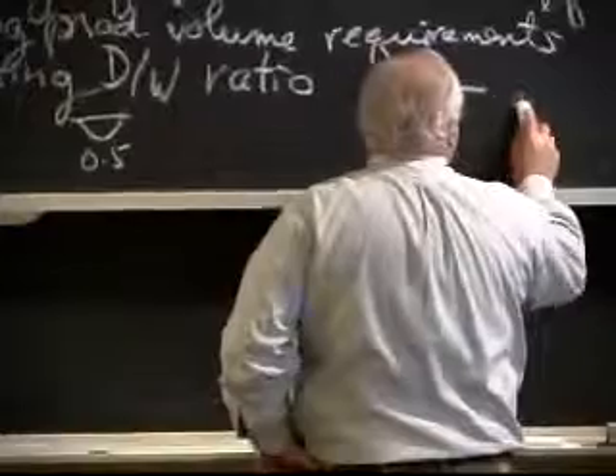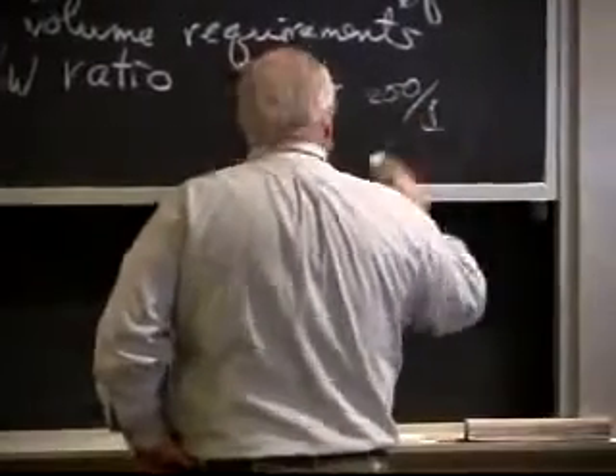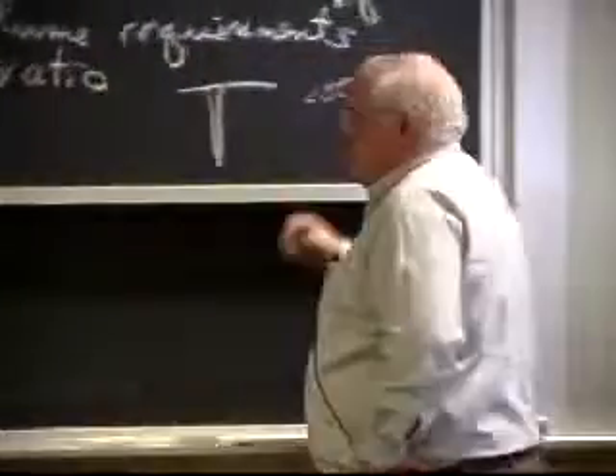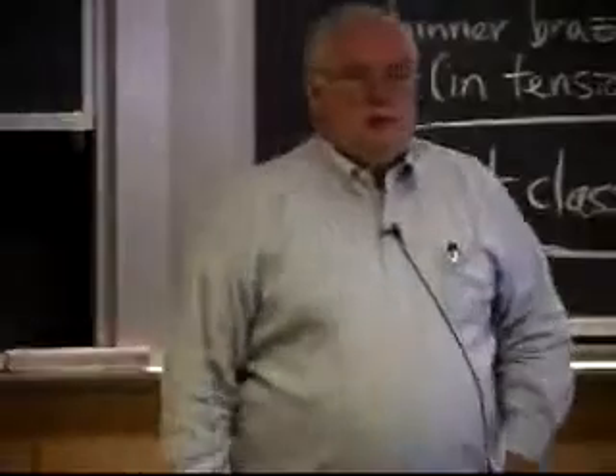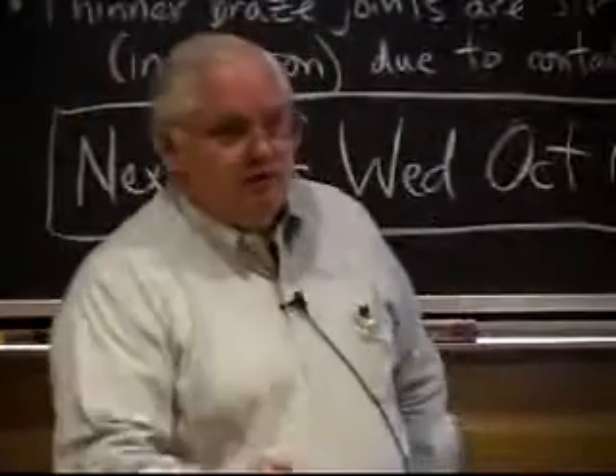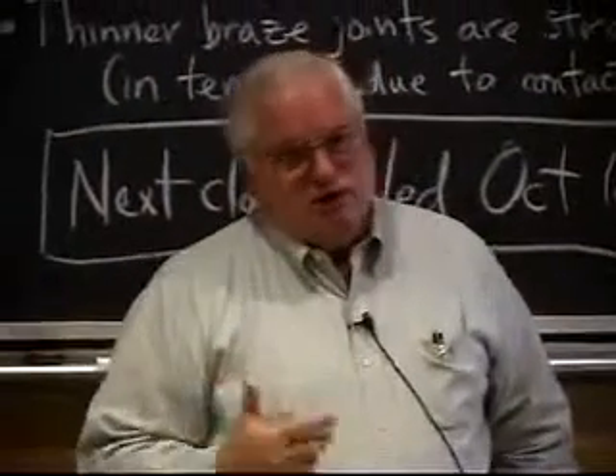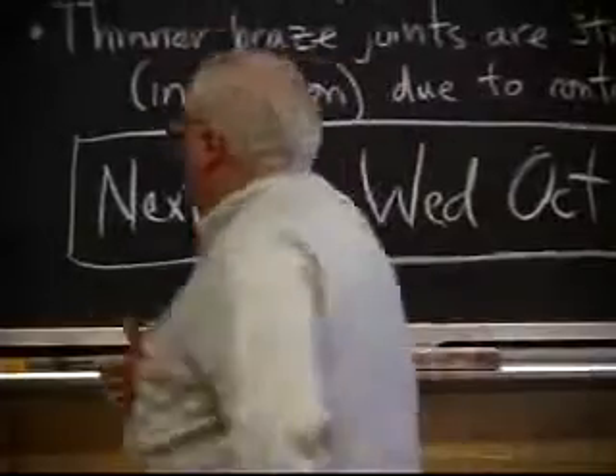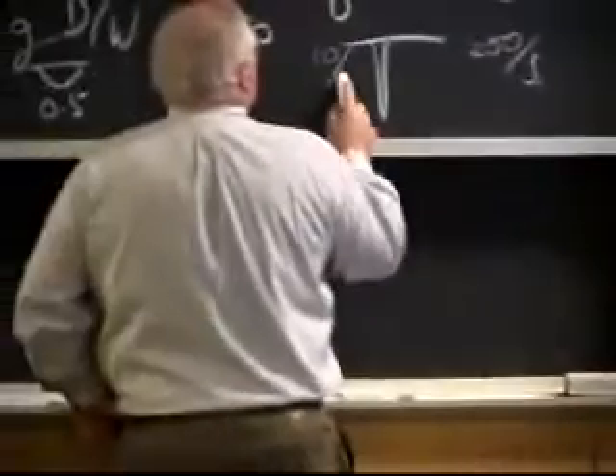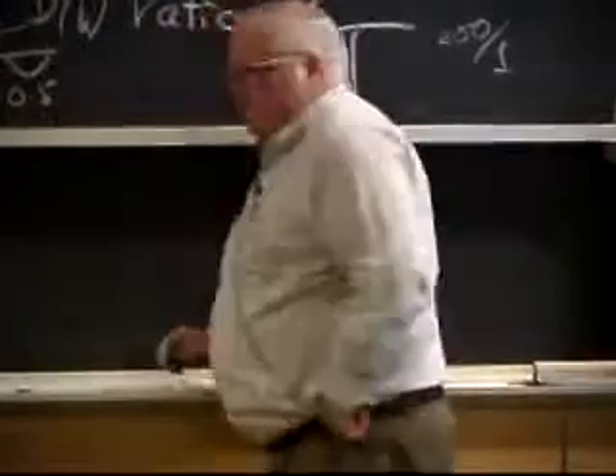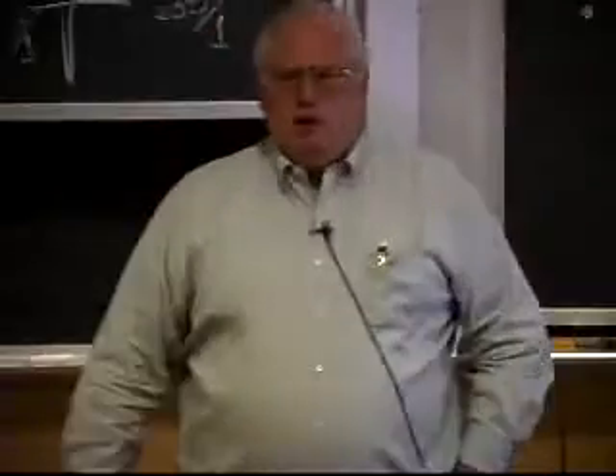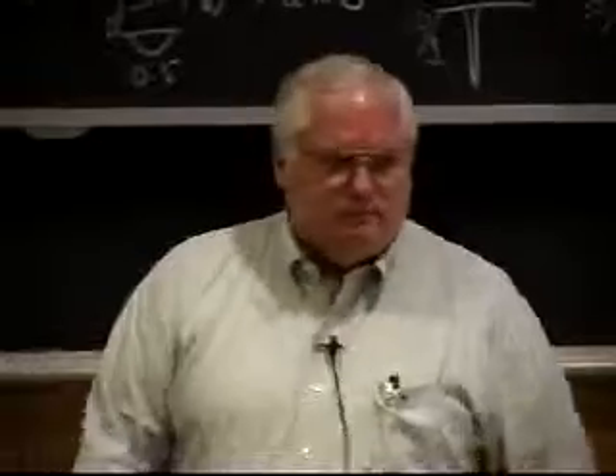It turns out the Welding Institute has gotten, in the laboratory, depth to width ratios of 200 to 1 in aluminum. It's worthless, but they've done it, just for a research thing. The maximum you really want is about 10 to 1 from a practical point of view. Anybody know why you limit yourself to 10 to 1? Yeah, exactly.